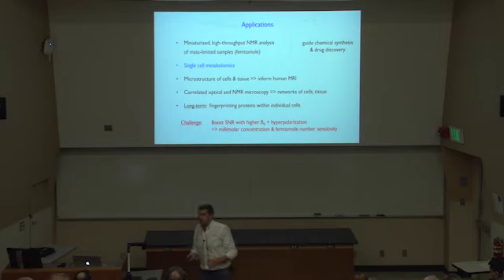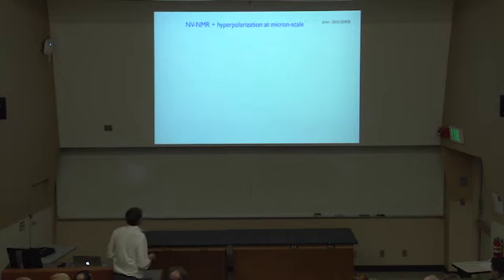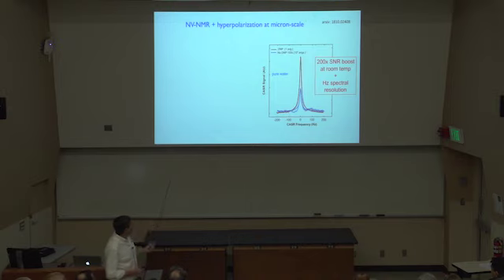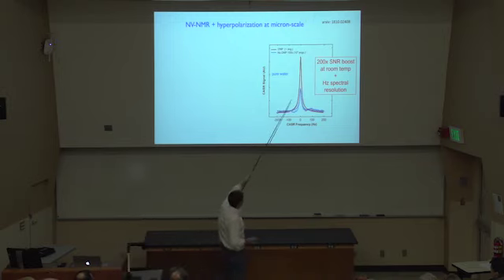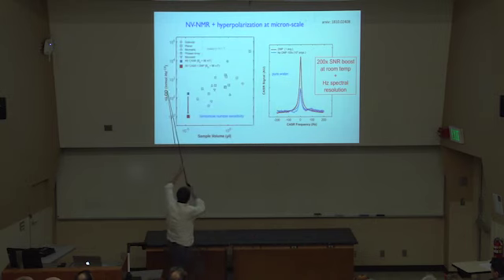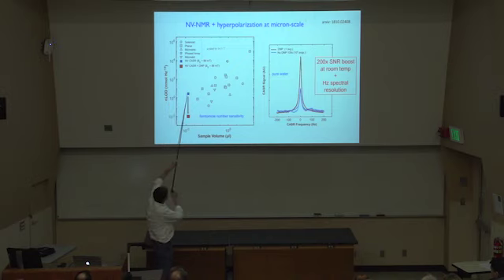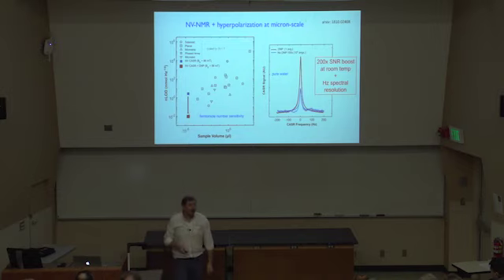So that's our challenges, and in recent months we've made progress by applying hyperpolarization techniques. This is now on the arXiv and being reviewed at a journal, whereby now we can get about a factor of 200x SNR boost and maintain the Hertz spectral resolution. So the red is the hyperpolarization technique, and the blue is without it, where you have 10,000 signal averages. It works very easily, so that now if you look at our number limit of detection, the smallest number of spins we can detect, and our sample volume, our Nature paper was here, and now we're down to here. And these are all the other previous results using microcoils and state-of-the-art NMR on the smallest length scales. So now we can really get down in both parameters to be far better than other technologies.